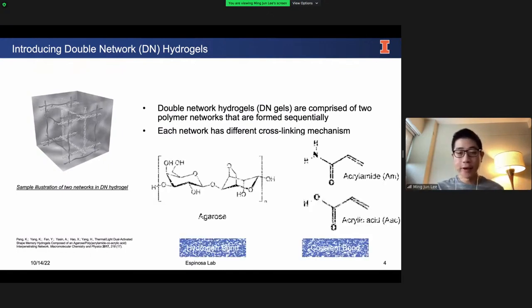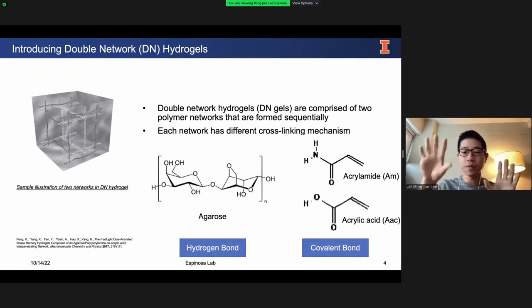Double network hydrogels are comprised of two polymer networks that are formed sequentially, one before the other, and they commonly have different cross-linking mechanisms between the first and second network. My particular system comprises agarose as the first network, and then a copolymer of acrylamide and acrylic acid as the second network. As you can see, agarose has a physical interaction: it gelates through hydrogen bonding, whereas the copolymer gelates through covalent bonds. So by controlling these two different interactions, I can time their sequential synthesis to make a double network hydrogel.